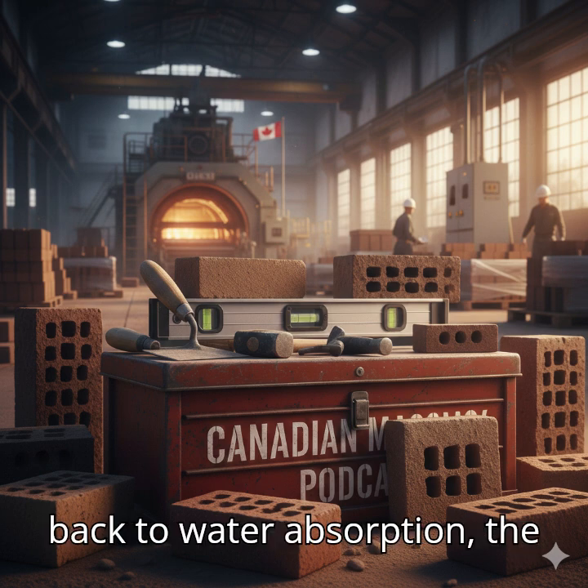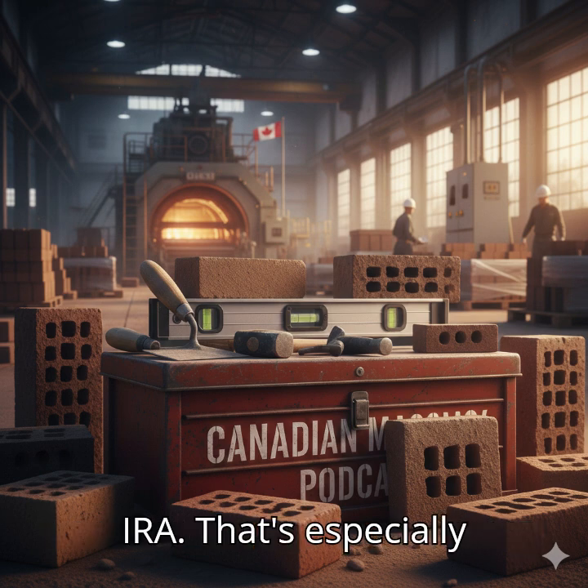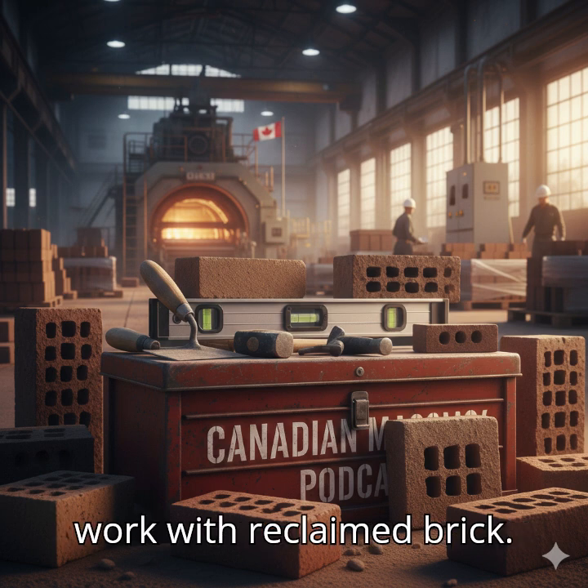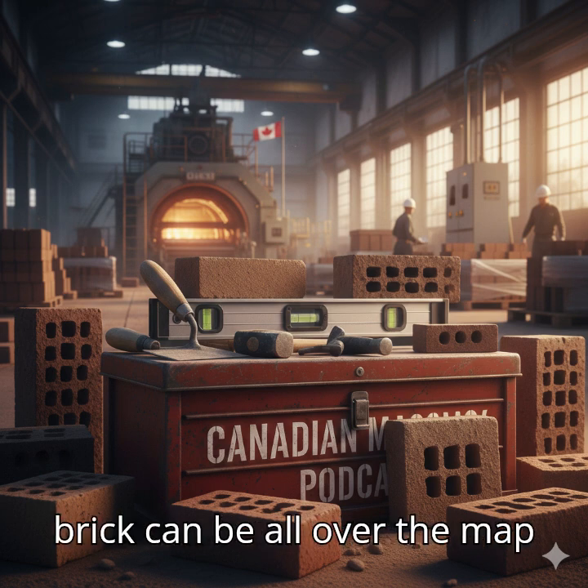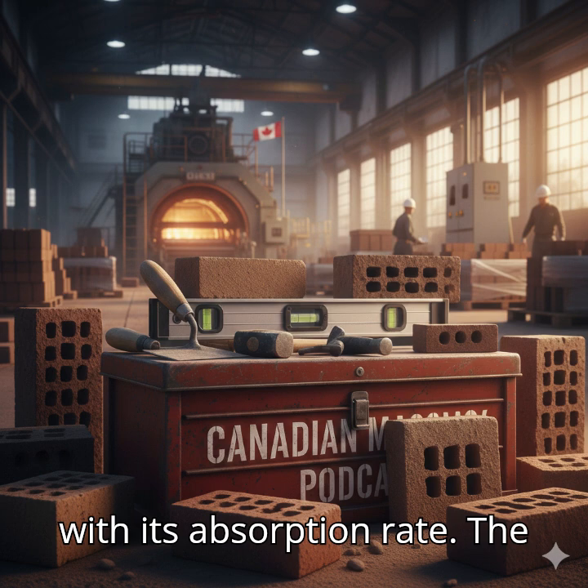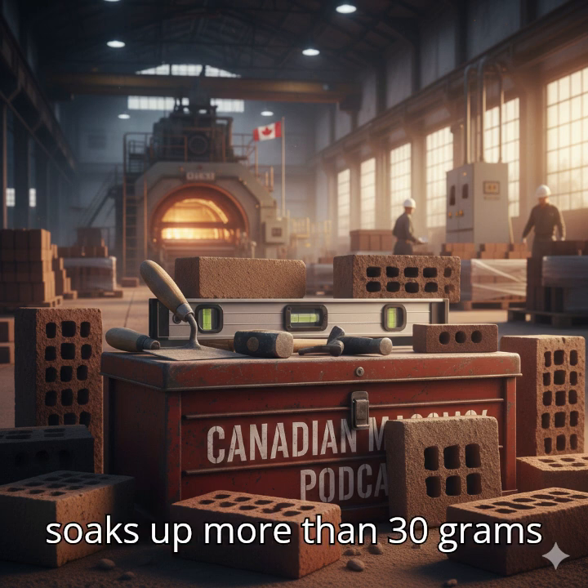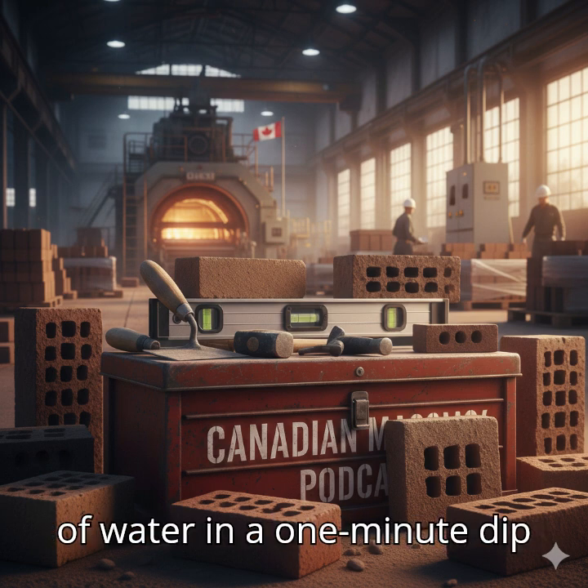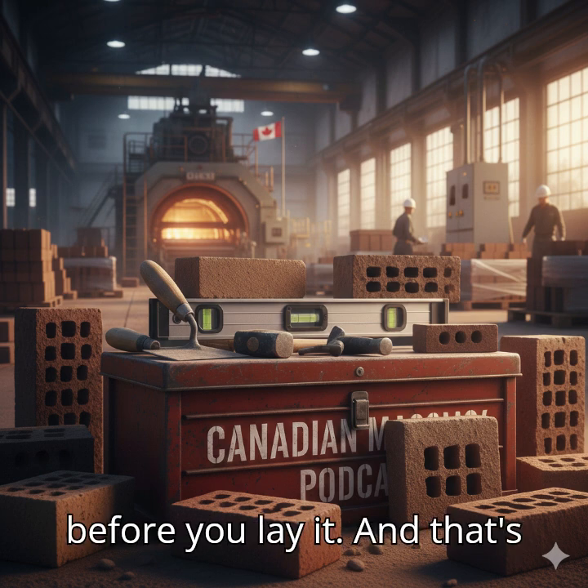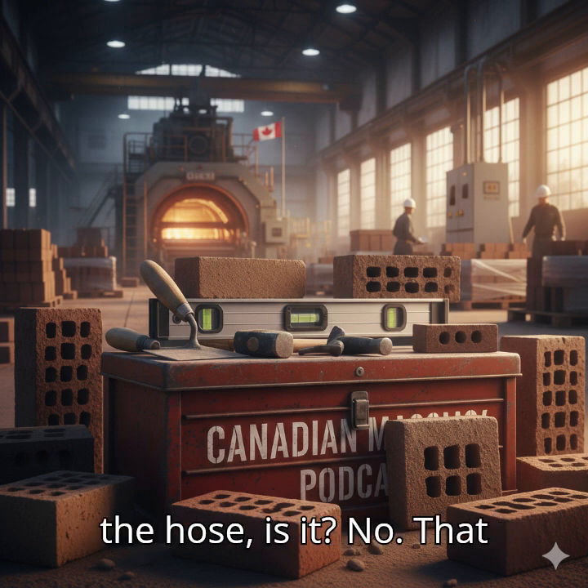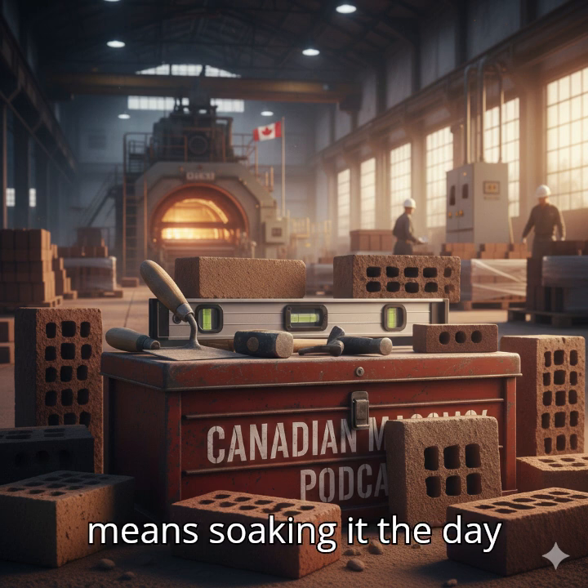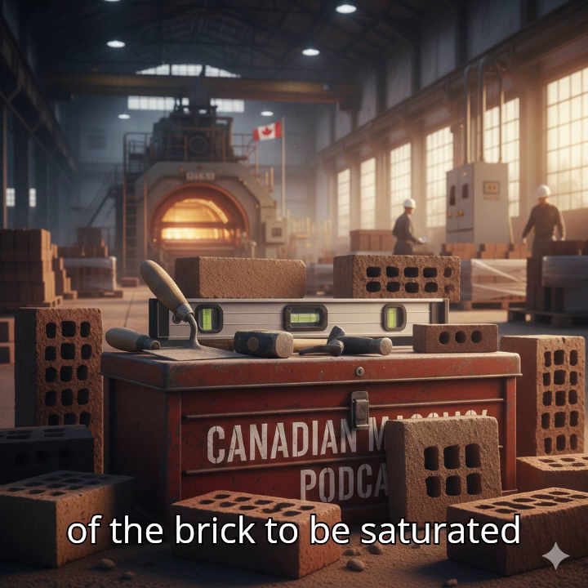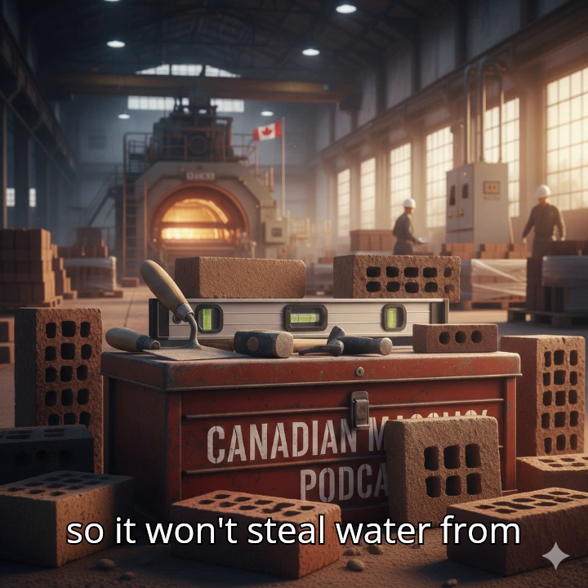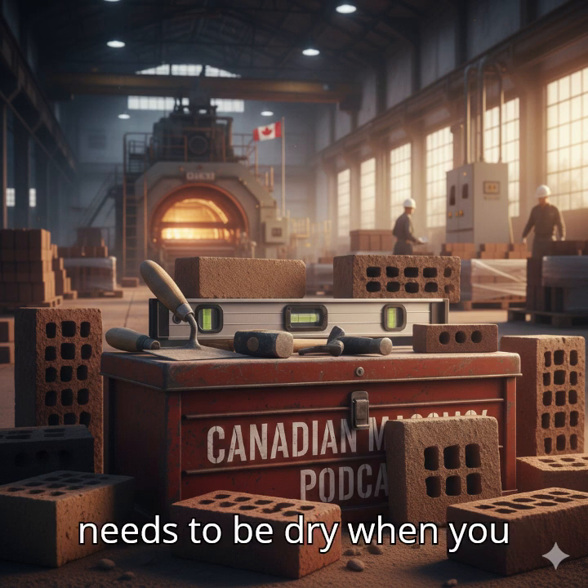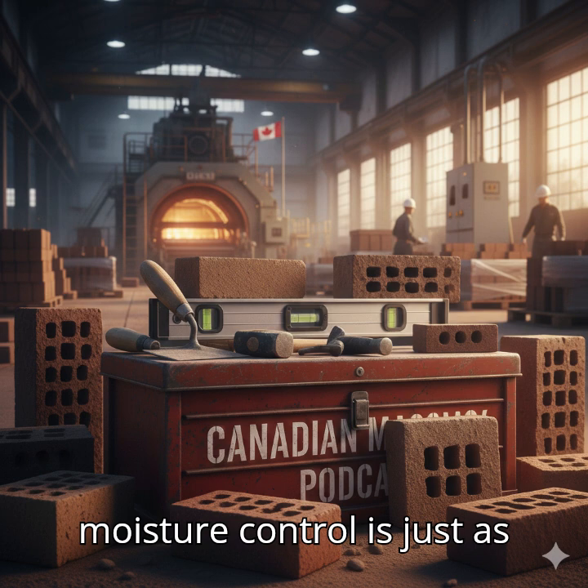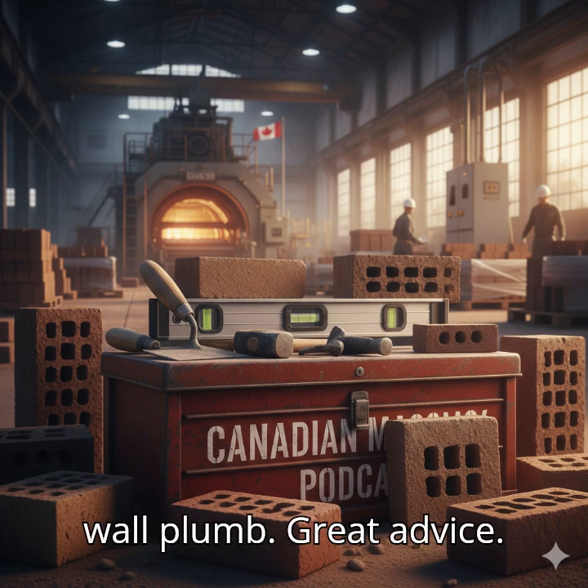And we kept coming back to water absorption. The IRA, that's especially important if you ever have to work with reclaimed brick. Oh, absolutely. Reclaimed brick can be all over the map with its absorption rate. The rule of thumb is if a unit soaks up more than 30 grams of water in a 1-minute dip test, you have to wet it before you lay it. And that's not just a quick spray with the hose, is it? No. That means soaking it the day before. You want the inside of the brick to be saturated so it won't steal water from your mortar, but the surface needs to be dry when you actually lay it. That moisture control is just as important as keeping your wall plumb.